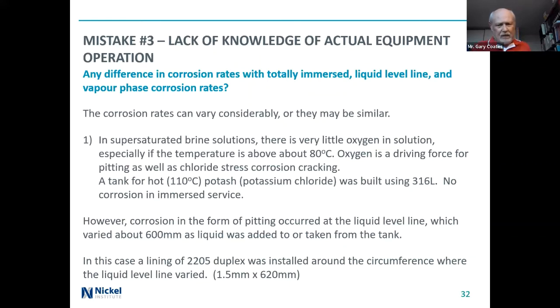And so the liquid level line varied in this particular tank about 600 millimeter, as liquid was added or taken from the tank. And so what they did is they installed a lining of 2205 in the liquid level line. It was about 620 millimeter wide sheet there, and that solves the problem there. So they kept the 316L tank because it worked in 90% of the applications fine.